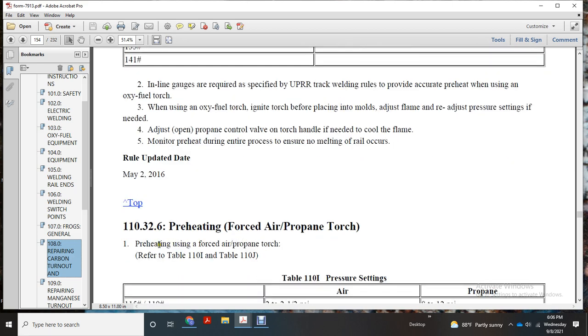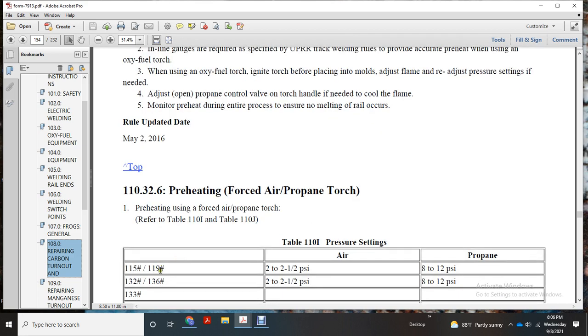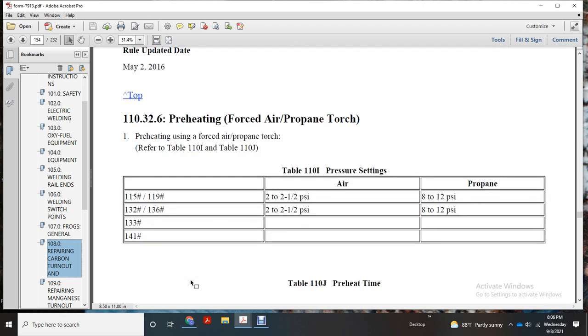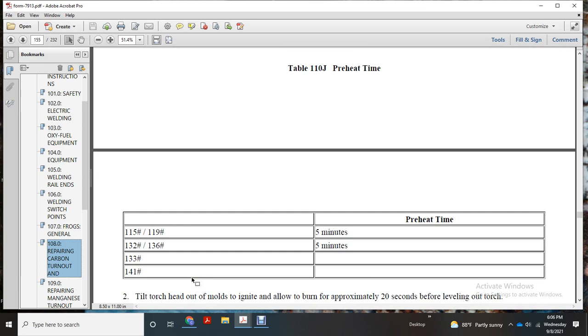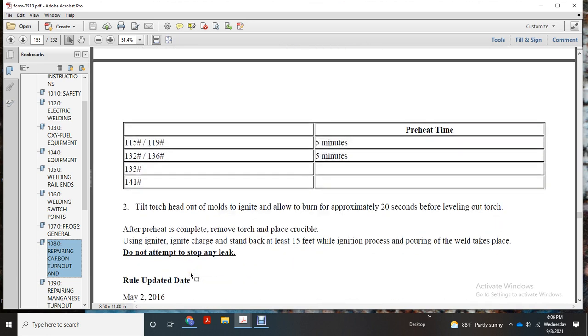Forced air propane torch. Preheat the forced air propane torch. For the 115 and 119, use 2 to 2.5 psi air and 8 to 12 psi propane, and that is also the same for the 132 and 136; 133 and 141 are not mentioned. The preheat time for the 115, 119, 132, and 136 is 5 minutes. Tilt the torch head out of mold to ignite, allow it to burn approximately 20 seconds before lifting out the torch.